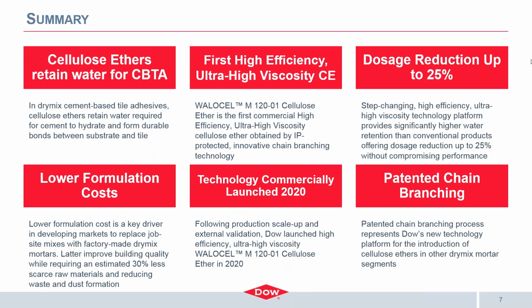Wrapping up, let me just summarize quickly the key learnings from the development of the ultra-high viscosity cellulose ether. As performance additives, as just mentioned, the cellulose ethers improve water retention. And in early 2020, Dow launched the high-efficiency ultra-high viscous Walocel M12001, which is the first commercial cellulose ether ever based on IP-protected chain branching technology. Due to this high efficiency, producers can reduce cellulose ether dosage by up to 25%. Formulation cost improvements support the adoption of high quality and more sustainable dry mix mortars also in developing markets.